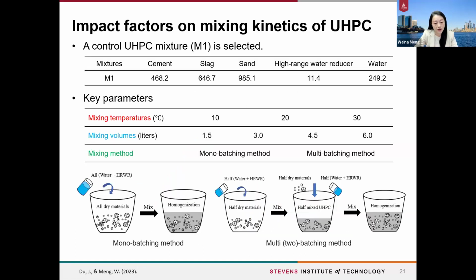So in our studies, we investigated 3 key parameters: the mixing temperatures, the mixing volumes, and the mixing methods. Specifically for the mixing methods, we have a mono batching method. It means we add all the raw materials at the same time and then add the water and the chemical admixtures and homogenize it at once. And for the multi-batching methods, it means that we equally divided the raw materials into 2 to 3 portions, and we add one portion and homogenize it, and then add the other until we add all the materials and homogenize them.